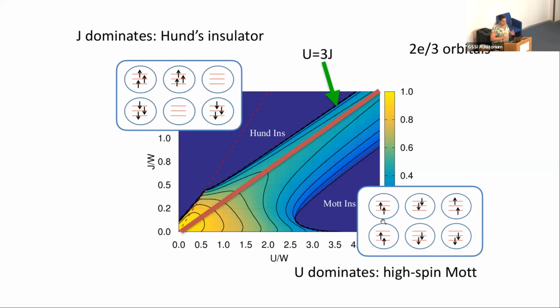So if you look locally now, you want to avoid double occupancy, and you can have on each site 2 electrons. This is the case of 2 electrons in 3 orbitals. You will accommodate 2 electrons in the 3 orbitals, and you have more or less this configuration with the spins randomly oriented because J is not important. If you are on the other side, J wants to maximize the spin and the local moment, as you say. So the best configuration that you can have is accumulating all the electrons in some sites, leaving others empty. So this is a typical configuration in the Hund's metal.